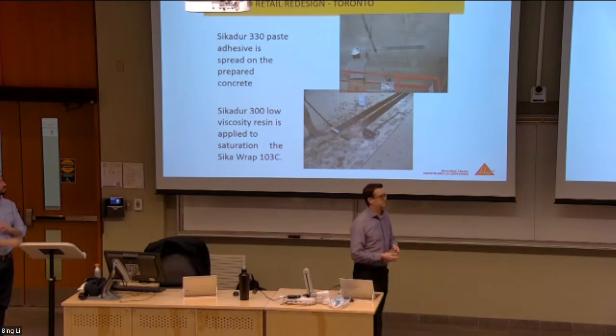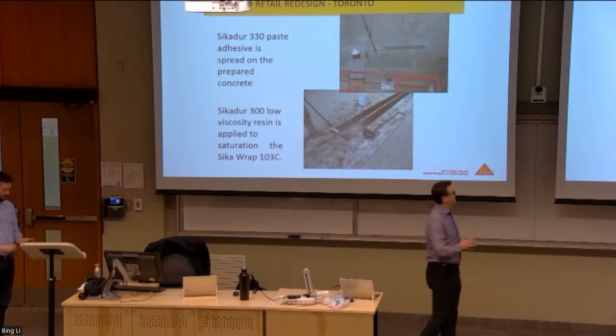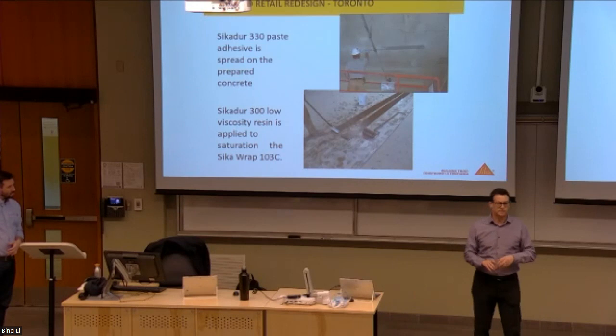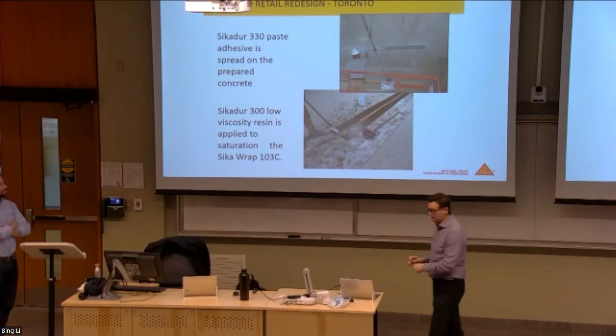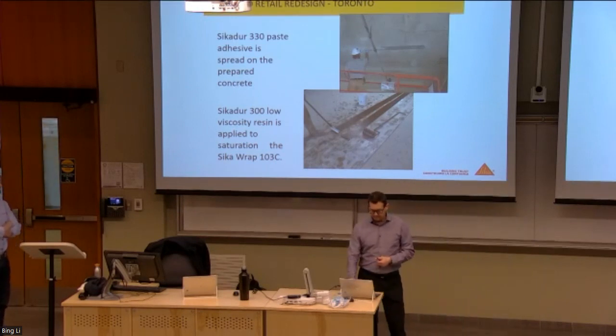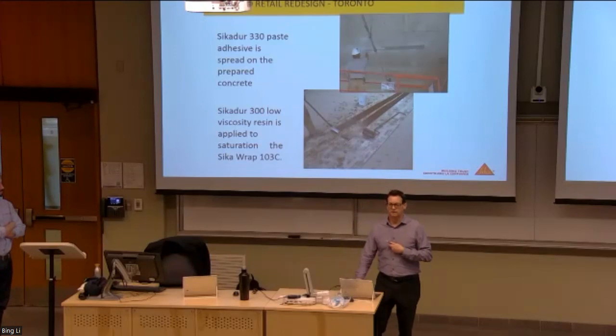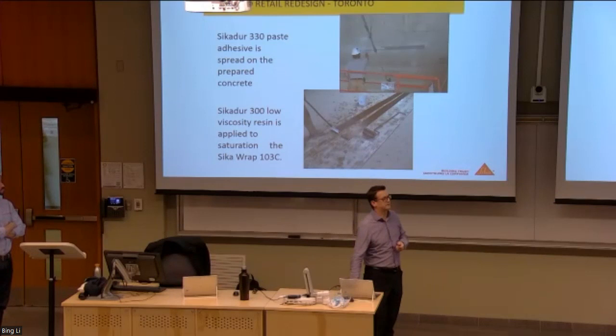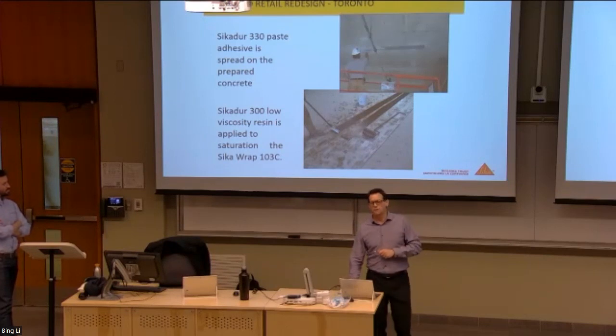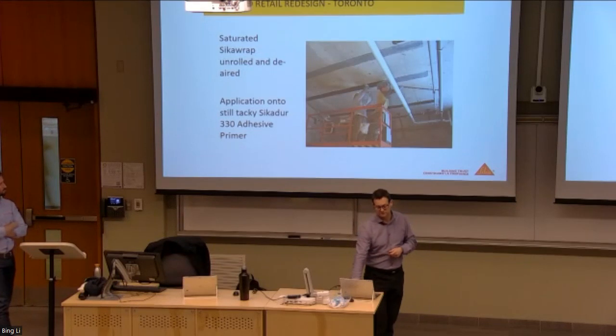Okay, the process is similar to what we showed earlier. This is a little bit different. So these are what we call pre-cured products. They come in that fabric, like the wallpaper. So you need to encapsulate that with an epoxy layer before it goes onto the surface. So what we've got in this illustration here is the epoxy adhesive going on the underside of the slab, and then the epoxy going onto the actual fabric itself, and then that would go onto the surface.